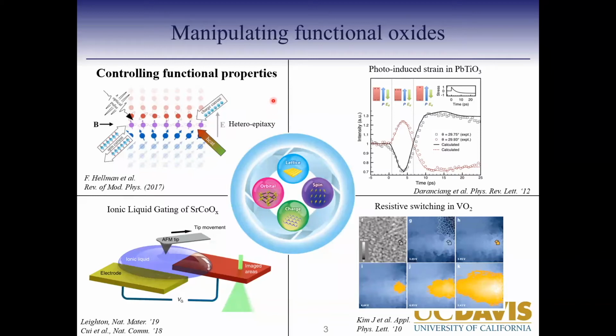And there are varieties of examples as to why we need to image these systems. One of the most commonly studied complex oxides, vanadium oxide, goes through a metal to insulator transition as you either heat it up or apply an electric field. And you can see here in this study that the transition starts with the nucleation of a metallic domain, which then inhomogeneously continues through the insulating phase, and the transition switches over.